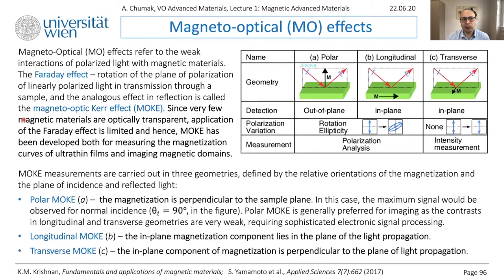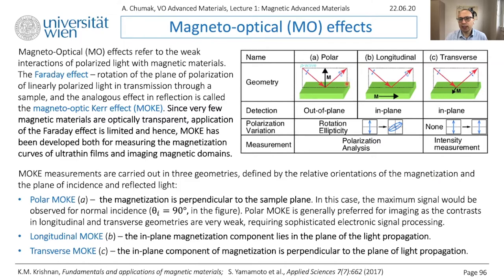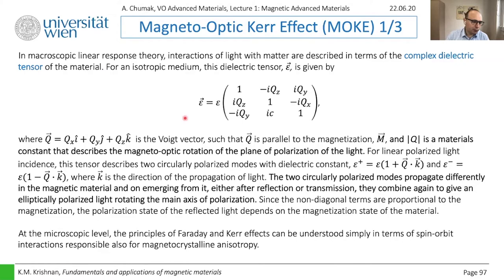As you understand, these effects are related to one another. The main idea is simple: you have a magnetic material with some complex magnetic pattern, you shine light onto the sample, and the reflected light will change its polarization. There will also be ellipticity of polarization — elliptical polarization. You just have to analyze the reflected light to get an understanding of the magnetic properties of your material. When we describe MOKE, we usually do so in terms of the complex dielectric tensor of the material. The electric permittivity ε — usually its square root gives the refractive index n.